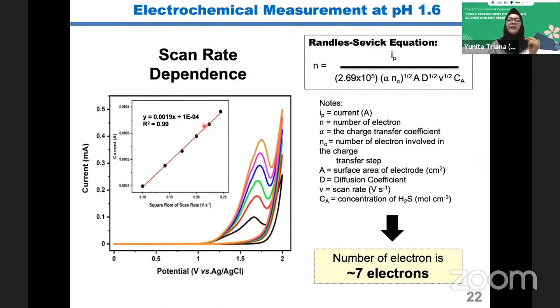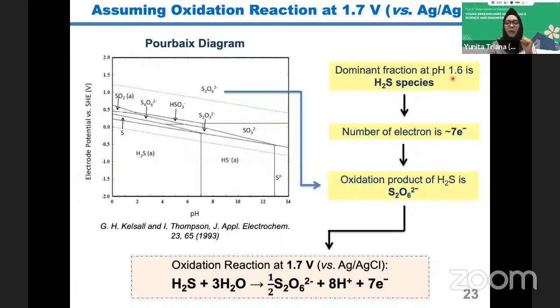The next investigation is about scan rate dependence. I did the scan rate dependence to check the electron number. From this step, I got the number of electrons is 7, with the oxidation potential at 1.7 volt, only one oxidation potential. So the dominant species at pH 1.6 is H2S, the number of electrons is 7, and the oxidation product of H2S is S2O6 2 minus based on this Pourbaix diagram. So my hypothesis is that the oxidation reaction at 1.7 volt is H2S plus 3H2O, and the product is S2O6 2 minus plus 8H plus via 7 electrons.